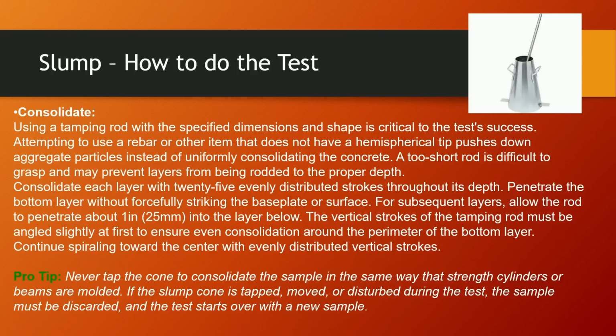Yes, they actually count the number of times you rod when you take the test. And really, if you've got a new testing agency, you should probably count for them too and see if they're doing this right. Pro tip, never tap the cone to consolidate the sample in the way you do when strength cylinders or beams are molded. If the slump cone is tapped, moved, or disturbed in any way during that test, the sample has to be discarded and the test has to start over with a new sample. So they shouldn't be whacking the cone.